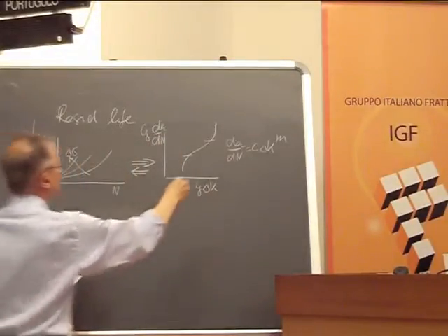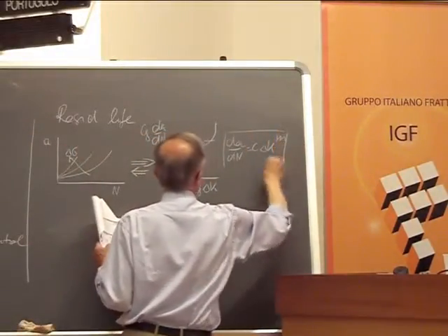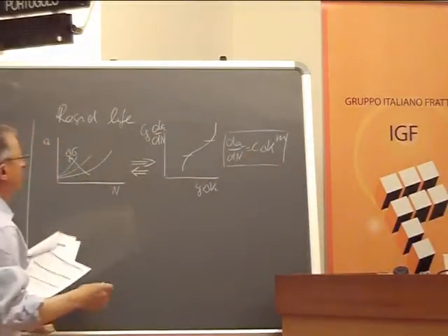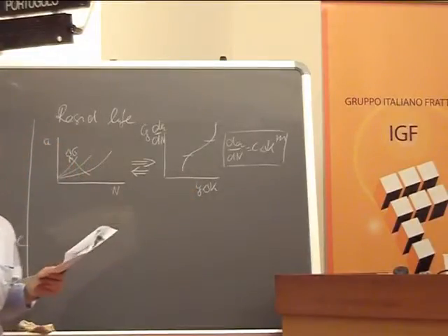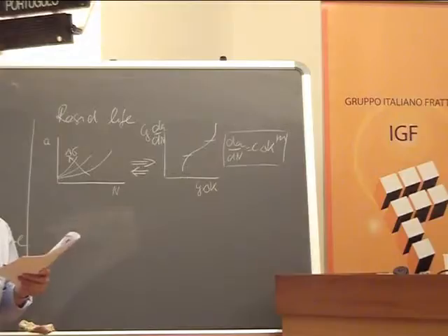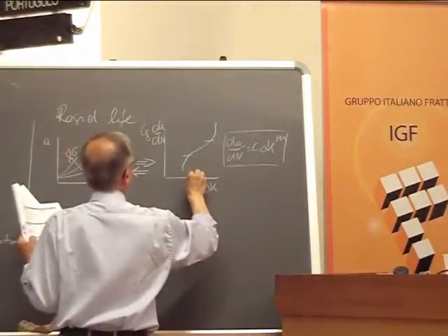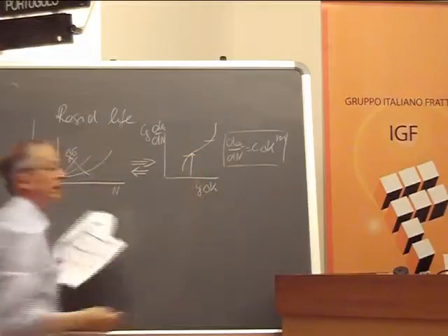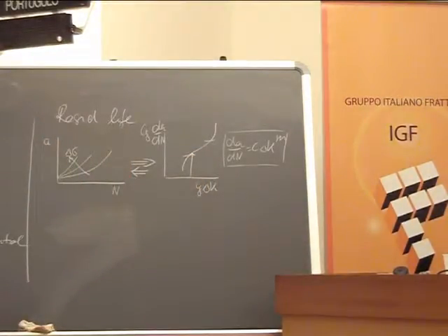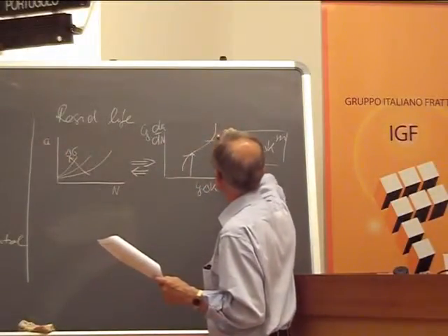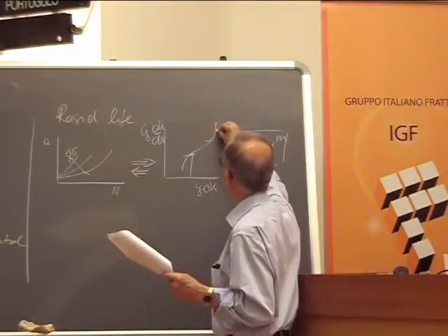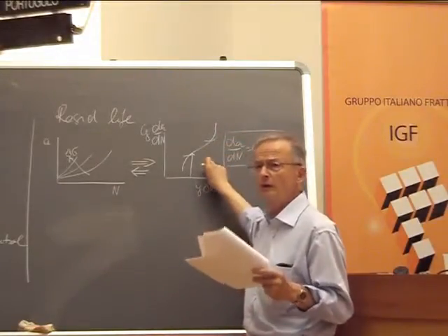For example, to stay here within the Paris region, we may have, the sketch is not so nice, an initial crack size that in combination with the applied delta sigma gives us a point where we enter the diagram here. And then we go up the diagram until the specimen fractures. So we can use the straight line relationship till final fracture, because here these are logarithmic scales.